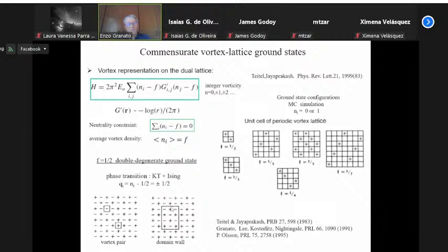But you can also have defects like domain walls. This is a closed domain wall. So there are two kinds of defects for this case, and therefore there are two possible transitions. You can have a Kosterlitz-Thouless transition, which is associated with these vortex pairs, or you can have an Ising transition associated with this domain wall. And it turns out that the transition in this system has been studied exactly because of this double possibility, and the transitions seem to happen very close together, with the Kosterlitz-Thouless transition slightly below the other transition. This has been studied by many people. I'll indicate some references here.